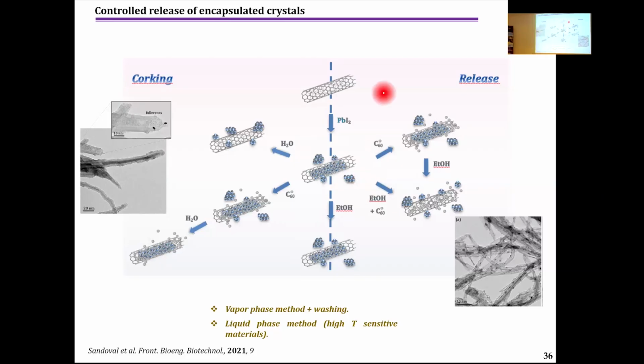So in this case, for example, for the release approach, we encapsulate lead iodide, which is used as a reference because of the contrast, not because of the utility of the material in biomedical applications, but because it's very easy to see on TEM. So what we did is fill nanotubes with lead iodide, then cork it with fullerenes in the gas approach, and there we use ethanol as release agent.